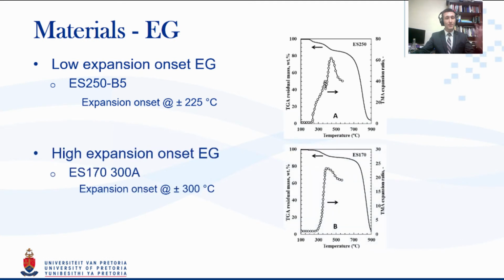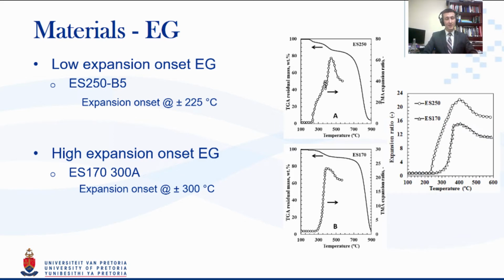I put up the TMA results for these two materials. You'll notice they have very different onset temperatures. This is as a direct result of that overoxidation that caused some of the layers to become further oxidized, having a lot of different other oxygen groups, which then release even more oxygen. But as an effect of that, it's a less thermally stable product.